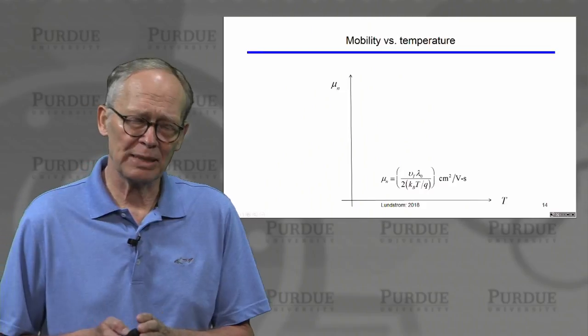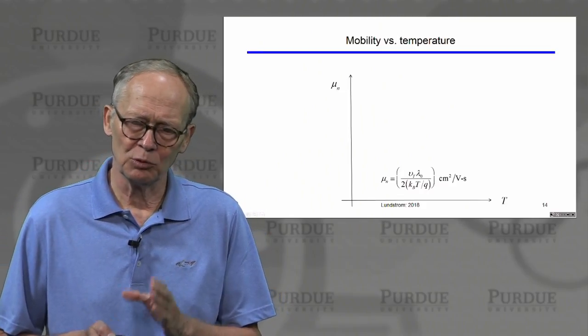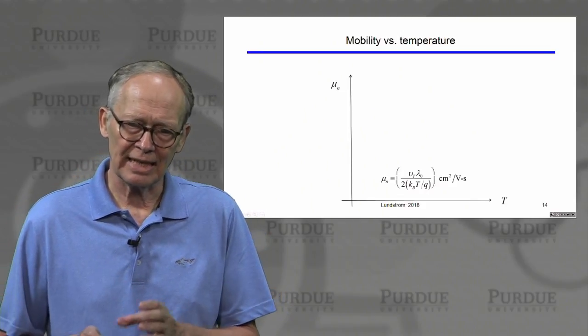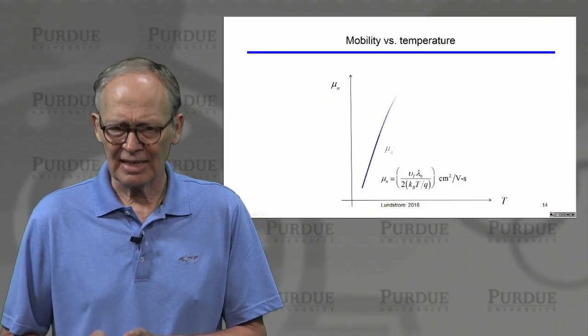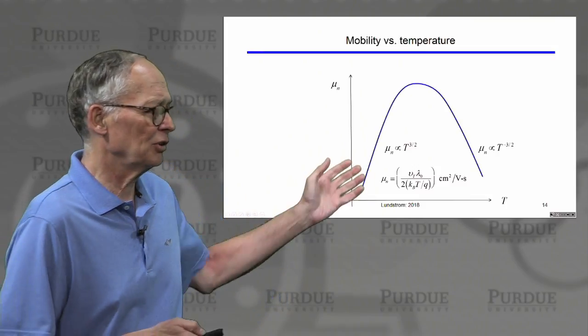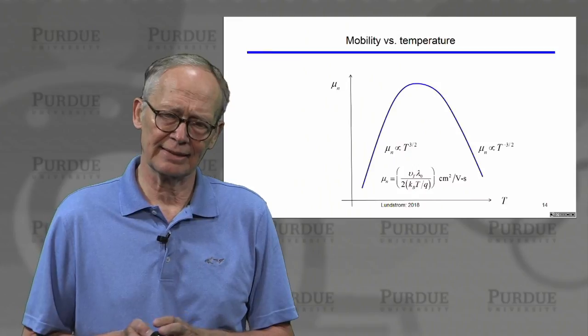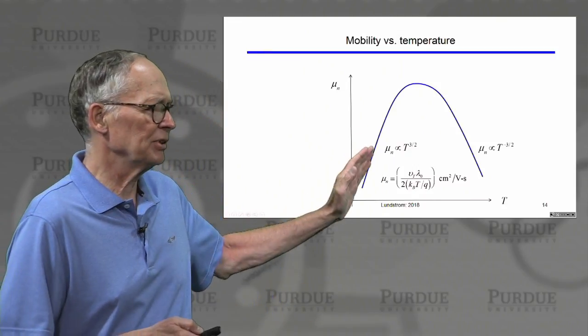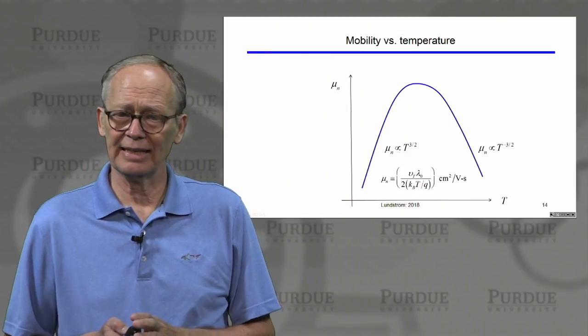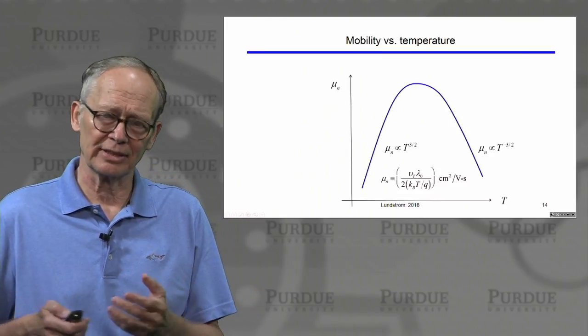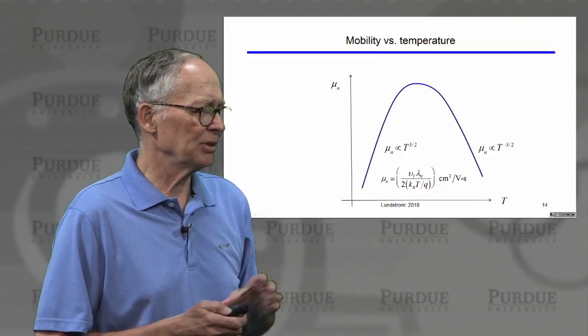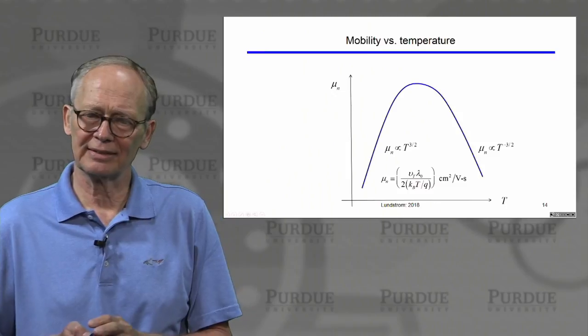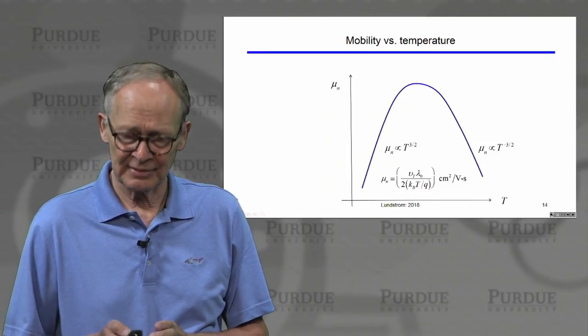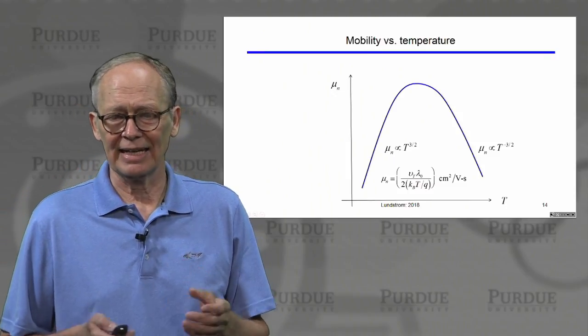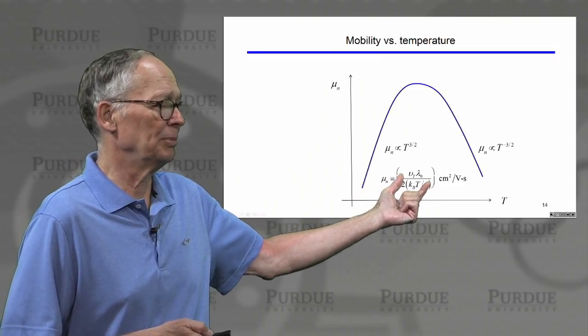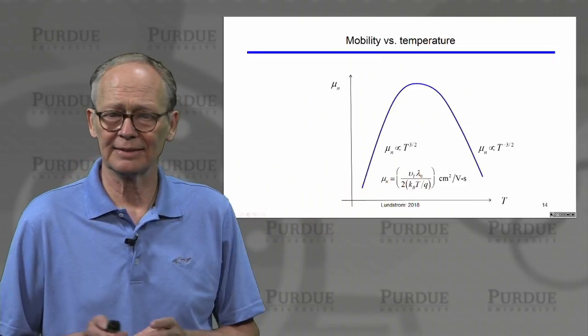Now, semiconductor people will also frequently plot the mobility versus temperature at a fixed doping density. And the mobility versus temperature might have a characteristic that looks like this. At low temperatures, it increases as T to the 3 halves in semiconductors like silicon and germanium. At high temperatures, it decreases with temperature as T to the minus 3 halves power. Now, what's going on here? Again, it has everything to do with scattering and thermal velocities.